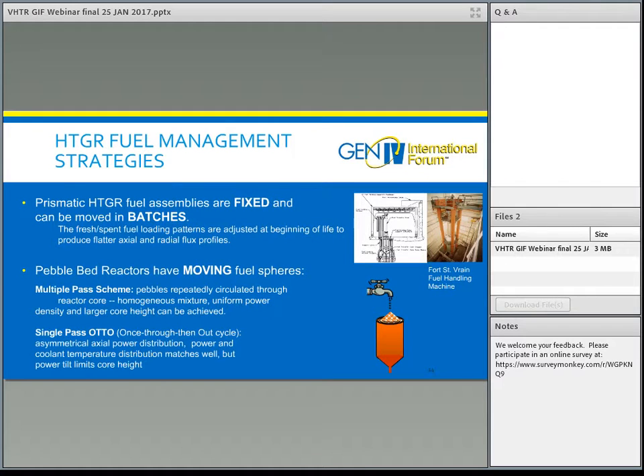Obviously, this leads to different ways of managing the fuel and the fuel loading within the reactor. In a prismatic high-temperature gas reactor, the fuel assemblies are fixed together, and they're moved around in batches. This picture from the Fort St. Vrain reactor shows a fuel handling machine that moved and adjusted the location of the large fuel assemblies within the reactor as time went on, and as fuel was used, could take the fuel out of the reactor and replace it with a fresh fuel assembly.